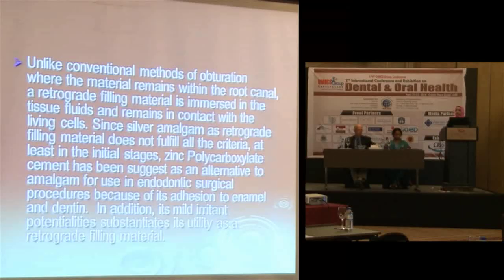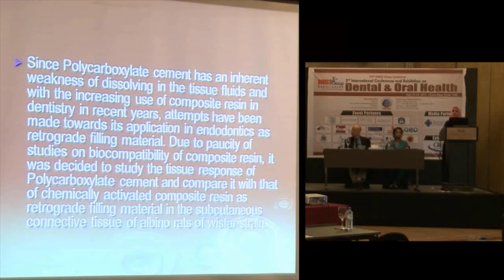Unlike conventional methods of obturation where the material remains within the root canal, a retrograde filling material is immersed in the tissue fluids and remains in contact with the living cells. Since silver amalgam as a retrograde filling material does not fulfill all the criteria, at least in the initial stages, zinc polycarboxylate cement had been suggested as an alternative to amalgam for use in endodontic surgical procedures because of its adhesion to enamel and dentine. Since polycarboxylate has an inherent weakness of dissolving in tissue fluids, and with the increasing use of composite resin in dentistry in recent years, attempts have been made towards its application in endodontics as a retrograde filling material.